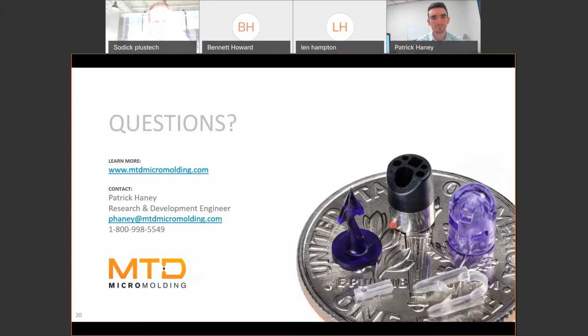Excellent. With small or micro shot parts, what is your typical target for cushion, or your screw most forward? That's something that again can be dependent on what the part looks like, or what exactly we're going for. One thing when it comes to our processing parameters is that sometimes we have to optimize them differently than we would in a macro environment, because the principles that you use to optimize something like cushion or hold pressure or injection pressure can't really be done on a small scale. So cushion is something that is dependent on the circumstances, but usually a few millimeters, somewhere in there.